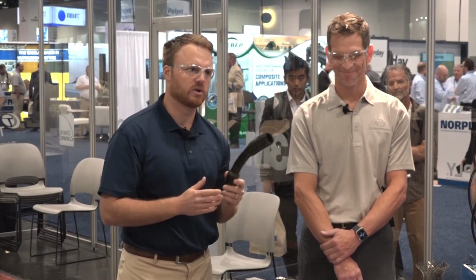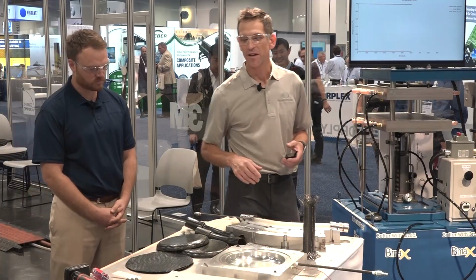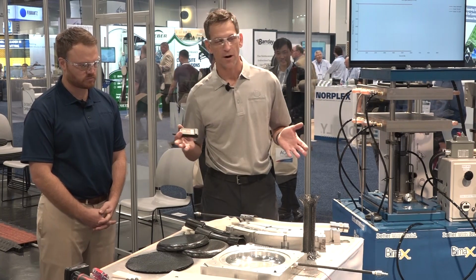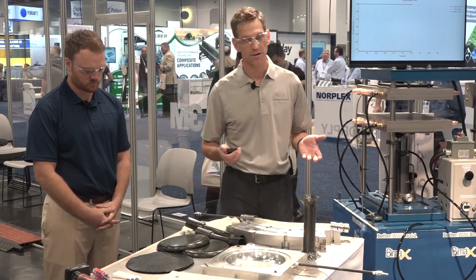I can cross-section this goofy tube anywhere along the length and tell you what the anticipated fiber orientation, areal weight, and cure ply thickness is going to be given a particular fiber volume. The main key is drapeability. So if you were to try and do this with unidirectional tape, you would likely have wrinkling problems because of the curvature. The braided architecture has very low crimp, so you get a high translation of the mechanical properties of the unidirectional tape. I wanted to cover our process that we're going to be using for our demo today.